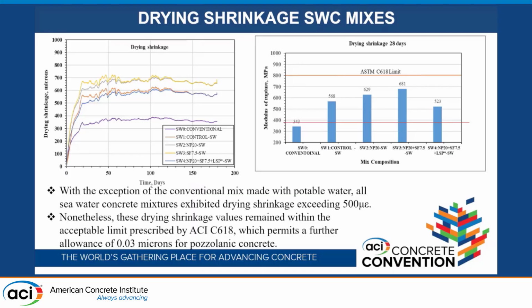The drying shrinkage was measured automatically by embedded shrinkage strain gauges, and you can see that with the exception of the conventional mix made with potable water, all the seawater concrete mixes exhibited drying shrinkage exceeding 500 microstrain. However, if you go to ASTM C618, which permits a further allowance of about 0.03 for pozzolanic concrete, then still all the drying shrinkage which was measured was within that ASTM C618 limit. But it's clear that with the addition of highly saline, hypersaline seawater, the shrinkage has increased significantly.